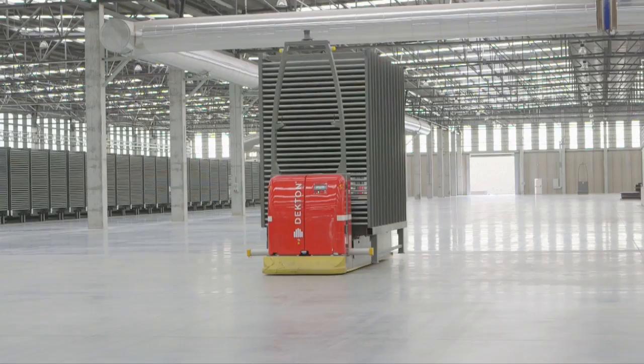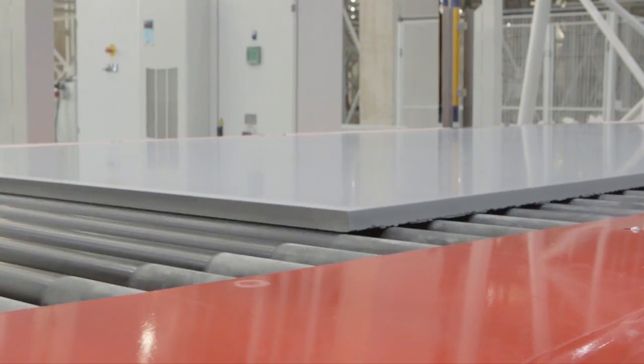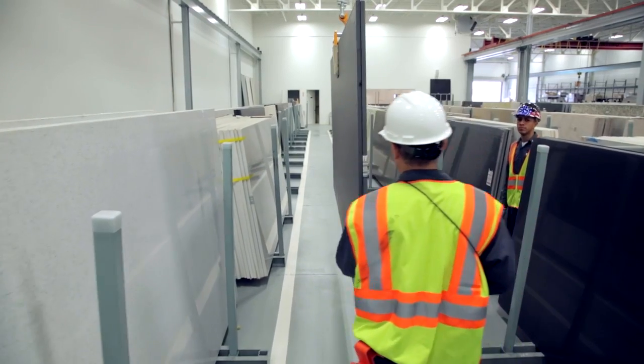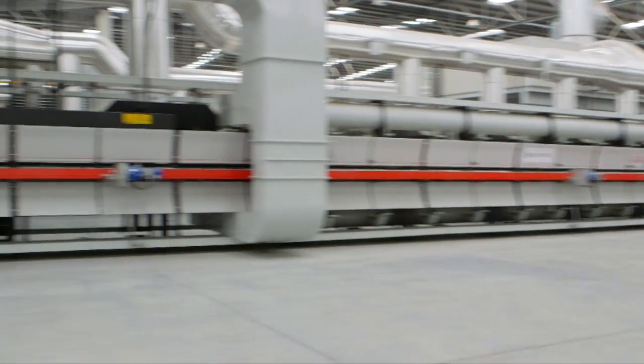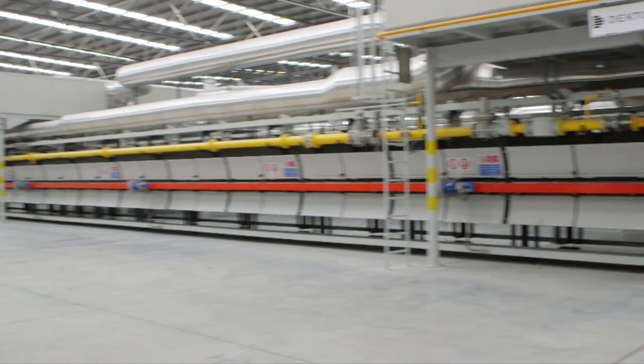Dekton's state-of-the-art production process at our factory in the south of Spain features a one-of-a-kind press which imparts 25,000 tons of pressure on each slab to help create a low-porosity material free of the micro-defects that cause tension or weak spots in other materials. Slabs are then exposed to temperatures exceeding 2,300 degrees Fahrenheit in a kiln more than 100